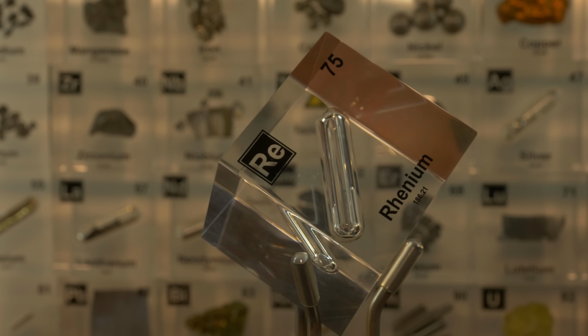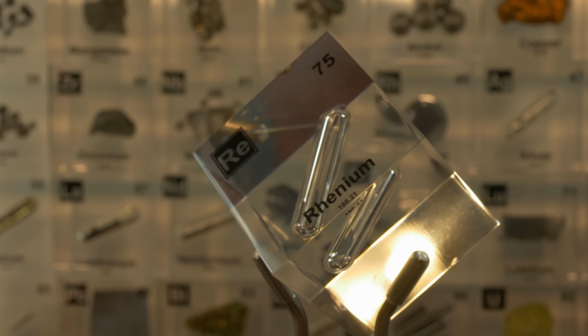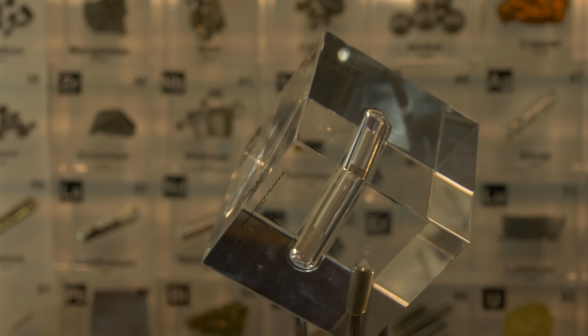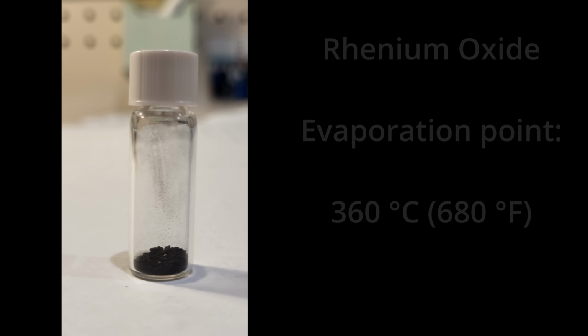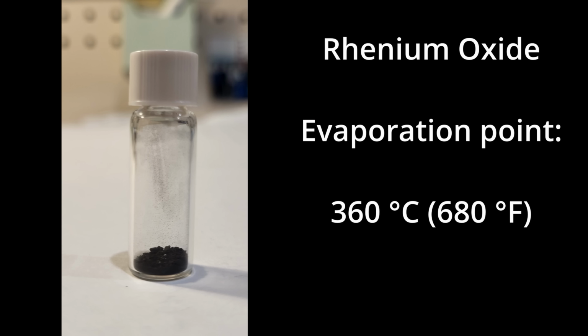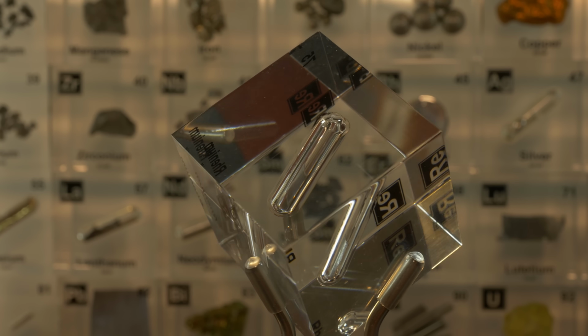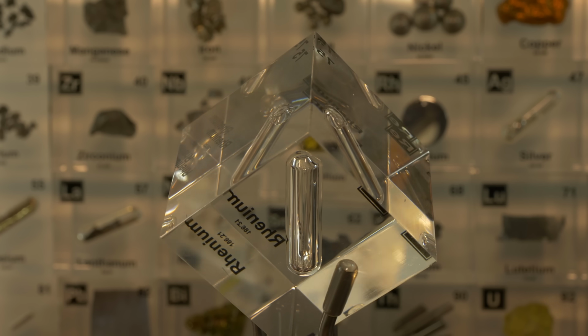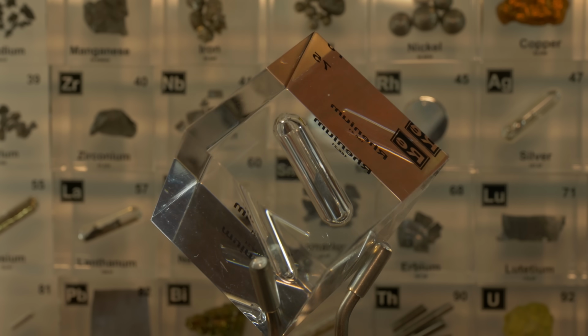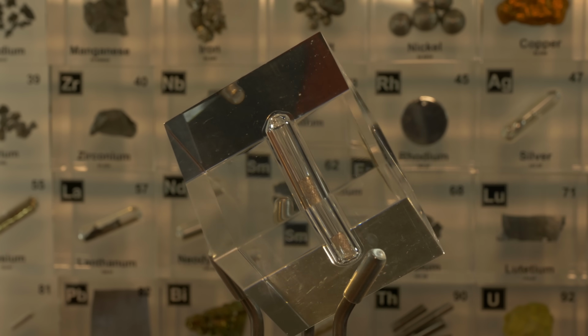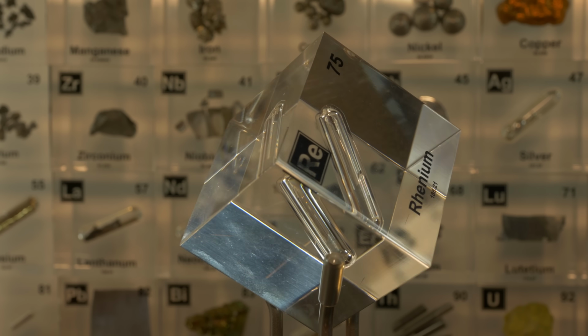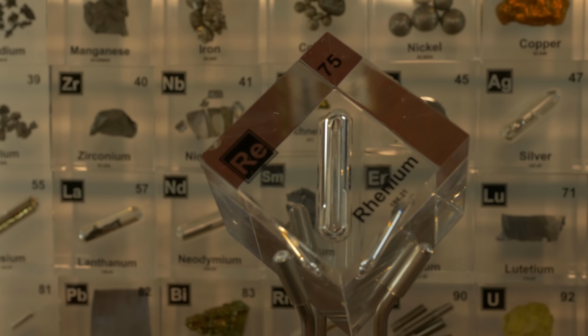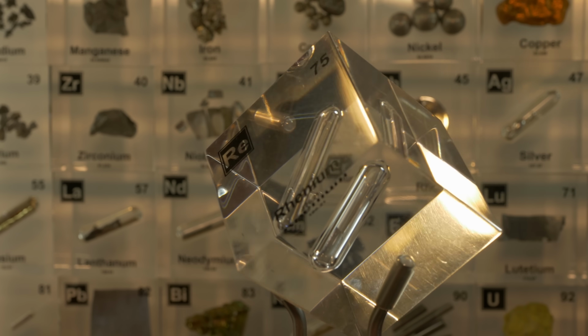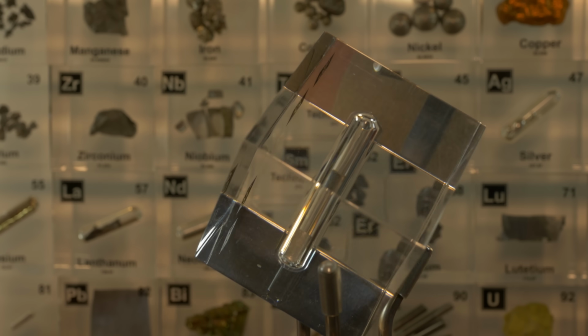When an electrical contact opens or closes under load, an electric arc can form, which often oxidizes and damages the contact surface over time. Rhenium has an interesting advantage. Its oxide is volatile and will evaporate at roughly 360 degrees Celsius. So if an arc forms an oxide on the rhenium contact surface, the resulting oxide can essentially vaporize away, leaving a clean metal surface behind. In effect, rhenium contacts can self-clean to a degree, maintaining good conductivity longer than some other metals in harsh switching conditions. Now this makes rhenium useful for contacts in certain high-performance switches and systems where reliability is crucial and maintenance is infrequent.